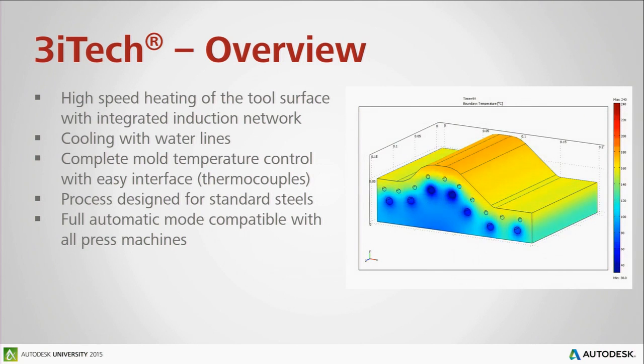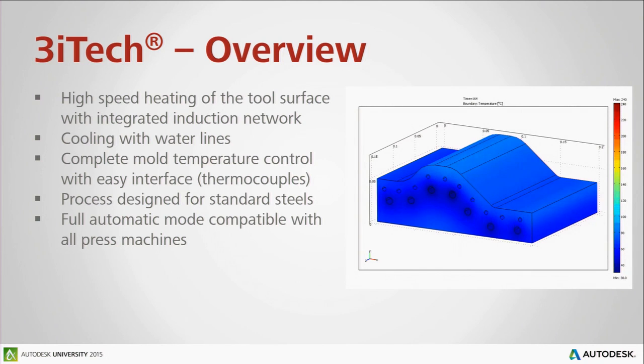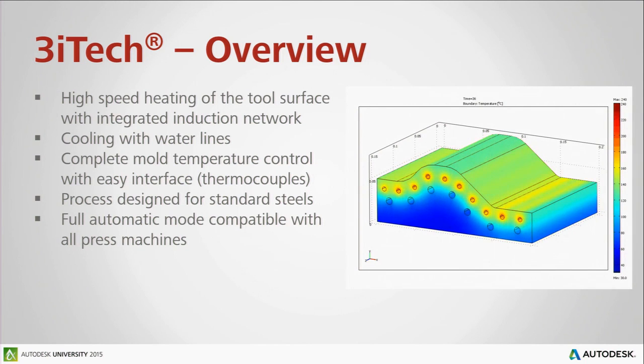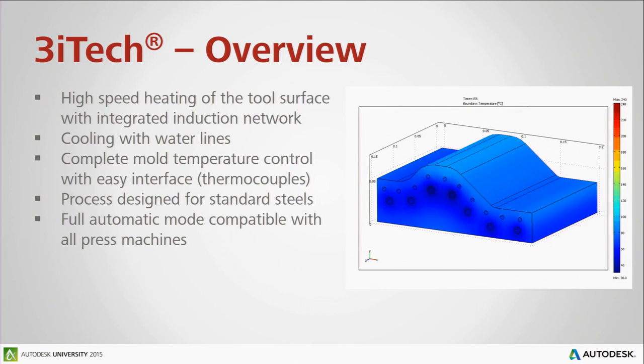It's a way to concentrate enough energy in a very small amount of mass, and drive that energy where you want and how you need it for your process. Because we don't really care that the whole tool is heating. We just want that small fragment of steel on the surface, like a flash heating, right before injection. And as soon as you're done injecting, you can drop your temperature. That's the key.